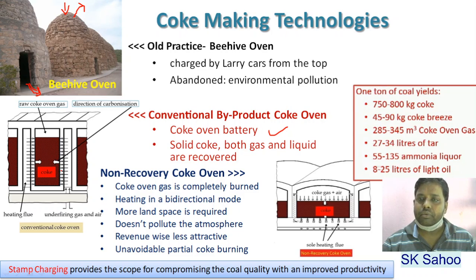The fuel is burnt inside the fuel chamber, and the solid coke, gas and liquid are recovered as byproducts. So it is called the byproduct coke oven process. If we look at the productivity or output of a conventional byproduct coke oven process, about 750 to 800 kg of coke is obtained, 45 to 90 kg of coke breeze, that means the fines, and coke oven gas, which is a very good fuel inside the steel plant, 285 to 345 cubic meters. 27 to 34 liters of tar, 55 to 135 liters of ammonia liquor, and 8 to 25 liters of light oil. So this makes the process more revenue generating.